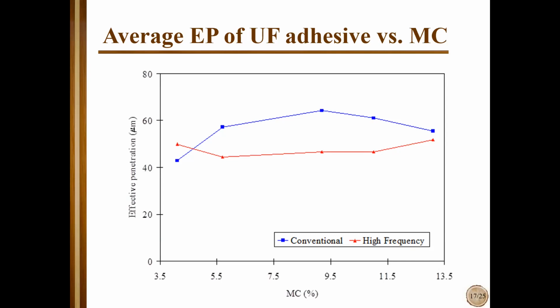And in this case, moisture content of wood doesn't play any important role. And as you see here, it's almost a line, no differences between different moisture content. But the blue line, which presents conventional heating, you see that there are differences in adhesive depth penetration.